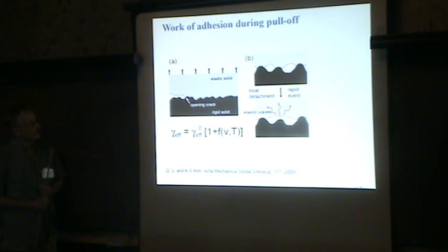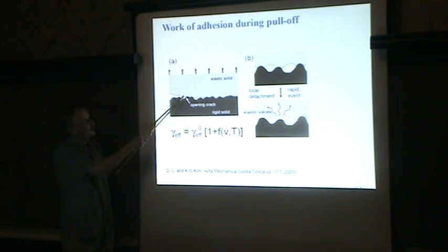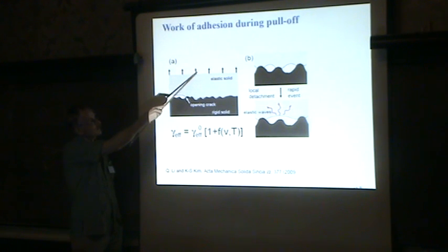So this theory I told you about might have some complications. It comes in the following way. I told you yesterday that removing an elastic solid from the substrate is best seen as interfacial crack propagation. So when we pull off, the crack edge will propagate inwards. But now we have a rough surface here. And when you start to pull, as I told you yesterday, you will have a stress singularity, where the stress starts to diverge and becomes very large. That means that a little in front of it, you can also start to get rather large tensile stress coming from the external load.